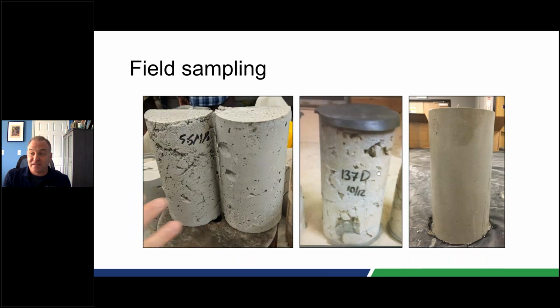Finally, I would say your quality control is only as good as the samples that you take. Here are some examples of various quality control samples that we've seen from the field. The one on the far right is what you would love every cylinder to look like. That's actually out of our own test lab in Colorado. You don't see very many bug holes. It looks pretty good. The sample on the far left, you can see that the person that was making the sample waited way too long, and the material was already curing when they tried to push it into the sample, and they were not able to properly rod it and remove voids. The same goes for the one in the middle.